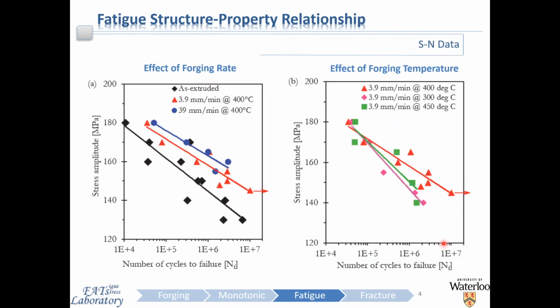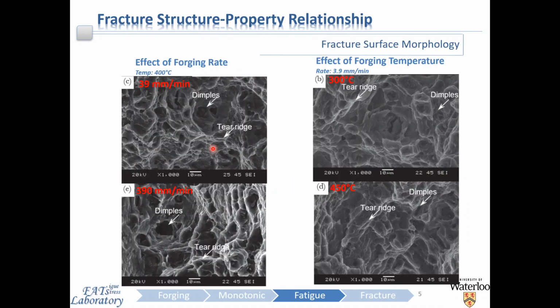Forging improved the fatigue life via a combination of grain refinement and texture modification, resulting in improved strength and ductility. Evidence of this is shown in these SN curves here, where a balance of strength and microstructural homogeneity favor longer lives. Thus, the most favorable forging conditions, of all the ones investigated here, was 3.9 millimeters per minute and 400 degrees Celsius.